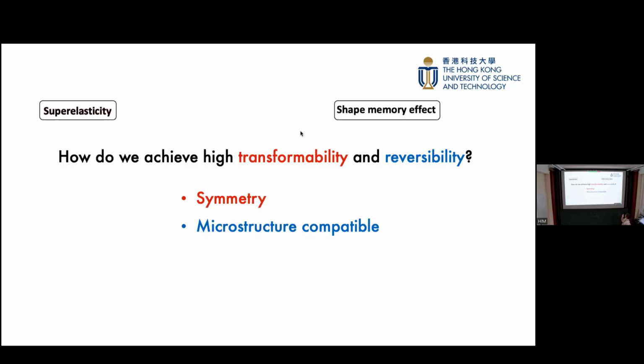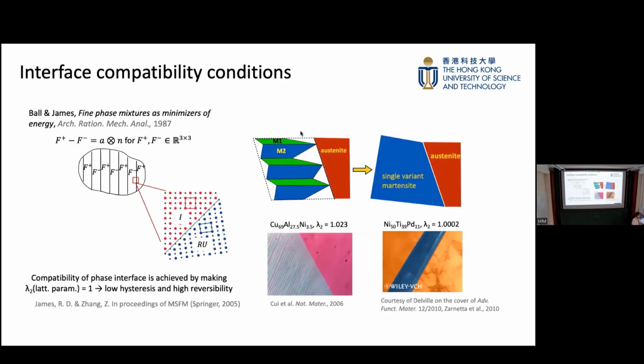And then how do we evaluate and understand the reversibility? So in previous years, people proposed the compatibility conditions for microstructure. In a single crystal, when a new phase nucleates from the reference phase, and they have different crystal structures, there has to form some interface. And if the lattice parameters are designed exactly right, they can fit together without any elastic transition layer. And we propose that if this condition is satisfied, the material becomes highly reversible. So that's the previous intuitive thinking.